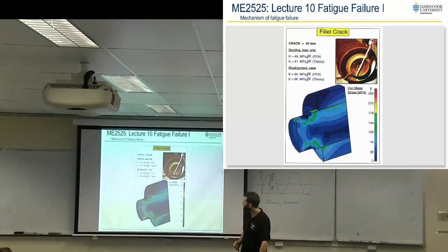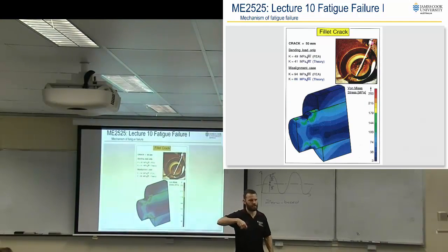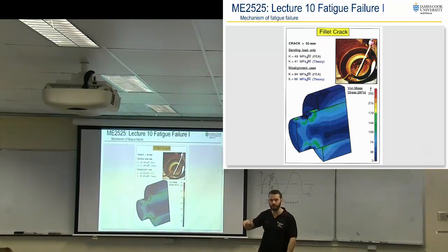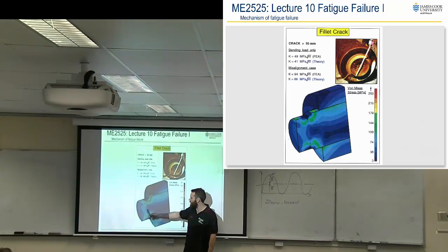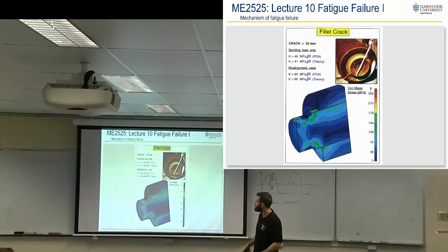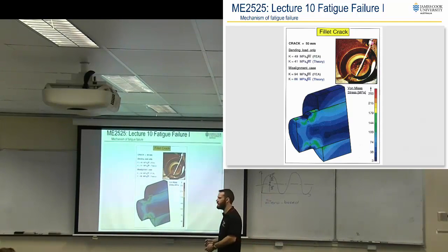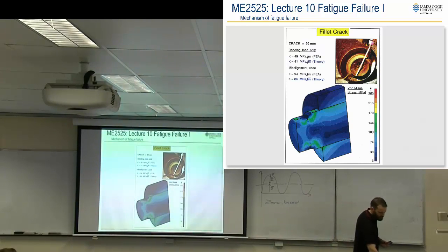I think it might have been Rockfield did to actually work out whether the loading history, whether the fatigue was actually enough to cause that cracking or whether something else was at play. And sure enough, they were able to simulate a crack tip and watch that crack tip propagate all the way through to the centre very, very slowly. And so be able to prove that it was that stress concentration that was causing the fatigue failure, and that whatever they had analysed, they missed something in the initial analysis of that shaft.